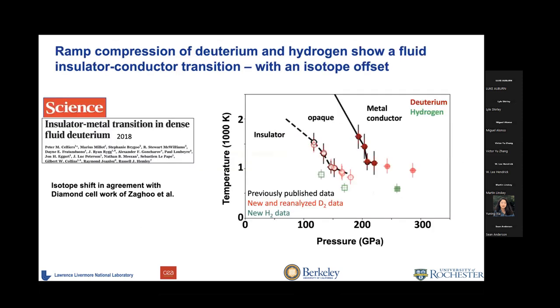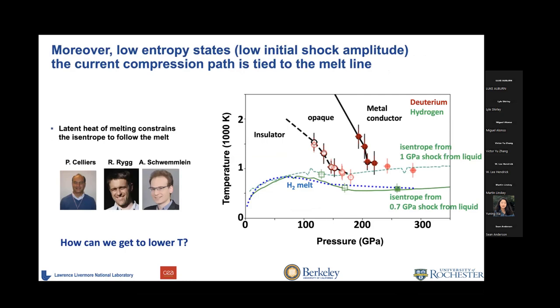This sort of shows an example of where we are. With these ramp compression waves, as you compress deuterium, it goes from insulating, and we're using red light, it becomes opaque to red light. Then as you keep squishing on it, at higher pressure and modest temperatures it becomes a conductor. We also did this with hydrogen. Notice there's a shift, a quantum shift in the behavior of hydrogen versus deuterium. And what this shows is the melt curve, which is shown in blue, and the two paths, these are the different ramp compression paths, green ones. The gas curve and the solid curve are two different initial conditions. But in almost all of the cases, the lowest temperature we can get so far is right at this solid boundary. So we're working really hard to get under the solid boundary.